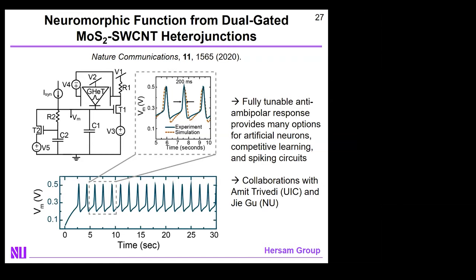Yeah. So it depends what you're competing against. If you wanted to achieve a similar spiking response in conventional silicon CMOS, for example, you can do it, and we cite those papers in this Nature Communications paper. But if you look at those devices, they tend to have at least 10, and in many cases a couple dozen transistors to achieve the same functionality. So the number of devices is actually quite low here. And the capacitors, I think, are very easy to implement. In fact, there's a lot of capacitance in our circuits that we try to get rid of. It's not hard to add a capacitance that comes for free wherever you have electrodes and dielectrics. So I think what really limits you is not the passive elements, but the active elements.